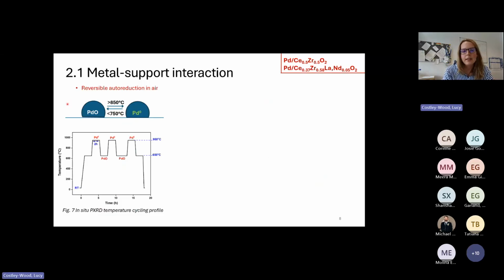So palladium oxide thermally decomposes to palladium metal at temperatures above 850 degrees. This will happen even in the presence of oxygen. That's just the temperature at which palladium oxide becomes less favorable than palladium metal. And it will reversibly reoxidize back to palladium oxide at temperatures below 750. So we're going to use this equilibrium and drive it back and forth to see the redox chemistry of palladium on the two different ceria zirconias. So in this in situ powder diffraction, we are cycling to force palladium metal and then force it to go back to palladium oxide and cycle back and forward between the two.